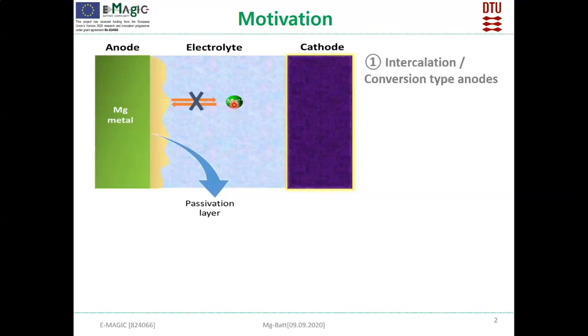The first solution is using intercalation or conversion type anodes. Basically, the normal intercalation anodes use bismuth, antimony, tin, or indium. But one of the biggest problems with this type of anode is the volume change associated with it. As well, in order to exploit the energy density of a magnesium battery, we should use magnesium metal in its elemental form. Then only can we completely exploit the magnesium battery in terms of energy density.